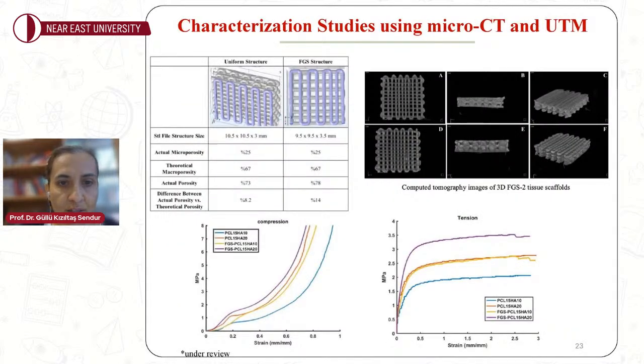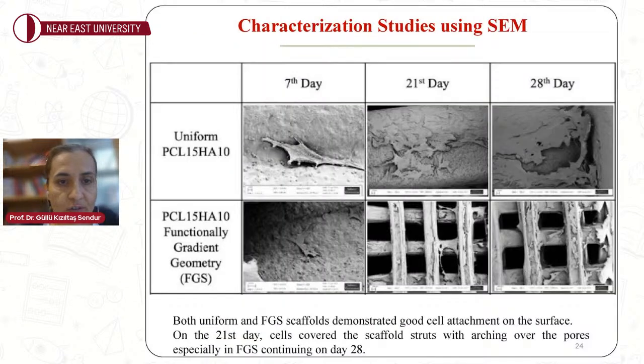Characterization studies show that the morphology was well maintained using micro-CT, and that the functionally graded structures that are the results of our design studies are actually delivering improved mechanical response, with higher strength both in compression and tension when you compare them with uniform scaffolds, demonstrating again the need for being able to design from scratch using formal methods and fabricate non-uniform and multi-material structures.